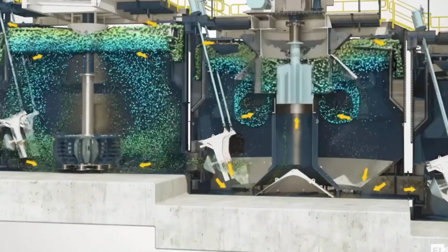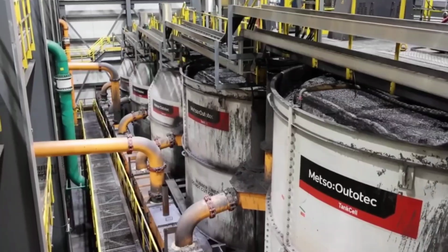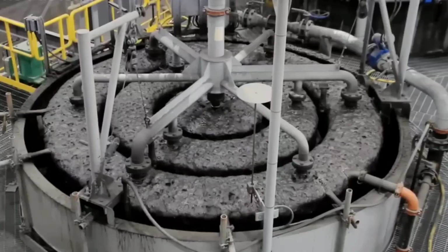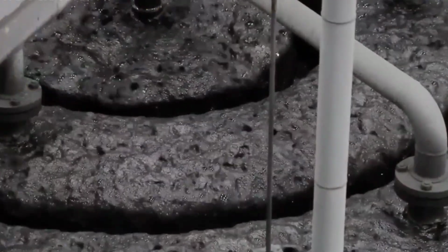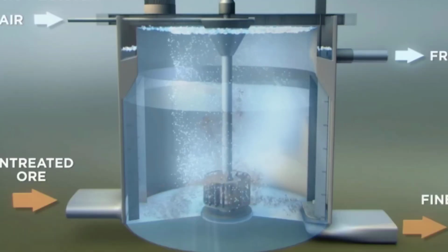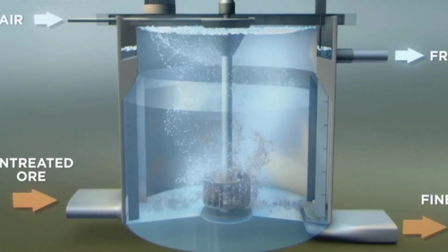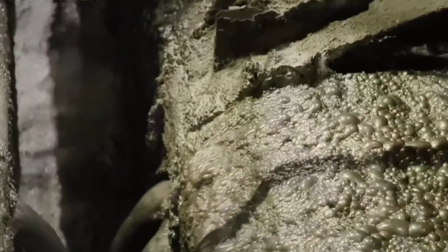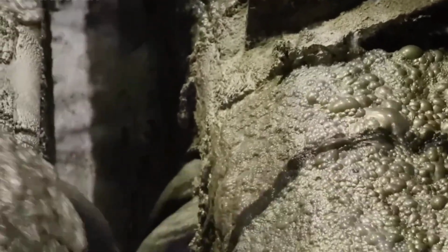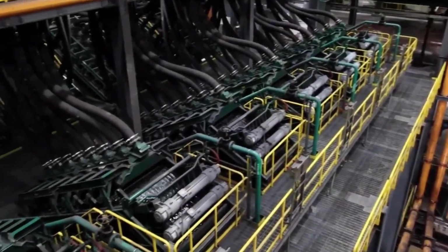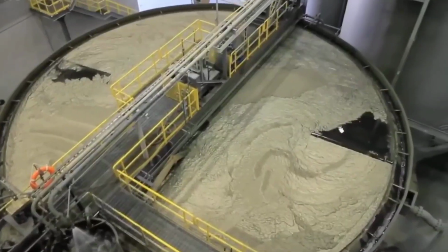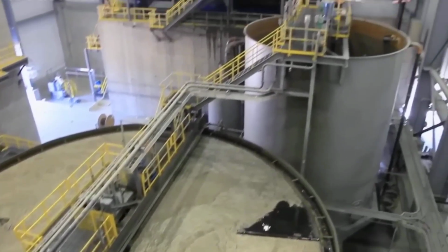Unlike the flotation of iron or common metal ores, this process with rare earths requires extremely high precision. Both the froth and the slurry must be carefully controlled, since rare earth ores have very low concentrations and are easily contaminated. The entire operation takes place inside a sealed tank equipped with dust collectors and chemical control systems to prevent the release of harmful dust or gases that may arise from traces of uranium or thorium within the ore. Each flotation batch typically lasts from 1 to 2 hours, allowing the valuable particles to adhere to the bubbles and float to the surface while preserving their elemental purity.